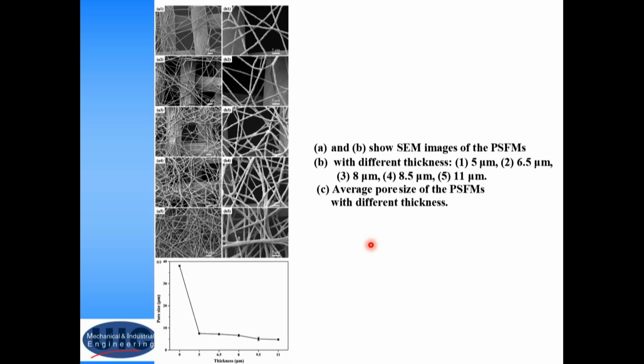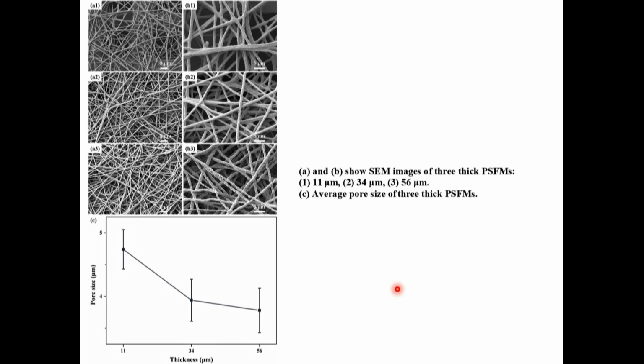So this is information about porosity depending on the thickness of the fibers and morphology. So I'll skip this over. This is one additional slide which shows the pore size as a result of the thickness, and essentially as the thickness increases, the pore size decreases. Okay, so the dependency is highly nonlinear, and the process essentially goes as mostly filling the pores when depositing additional fibers, so you diminish the pore size. So you end up essentially with pores on the scale of several microns, which is typical for electrospinning, and thickness can vary, and we vary up to essentially 100 micron.